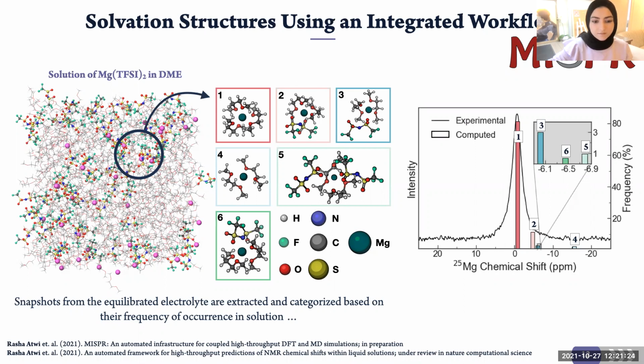In this case study, we performed cluster analysis from MD simulations and categorized these clusters into unique configurations, each representing a different type and number of solvent or anion species around the cation. And they also represent the exact chemical environment of the salt in the solution.